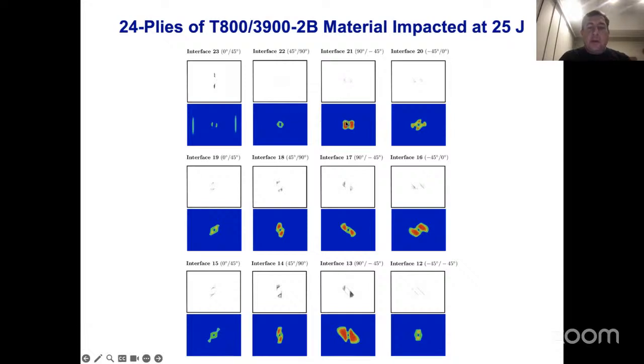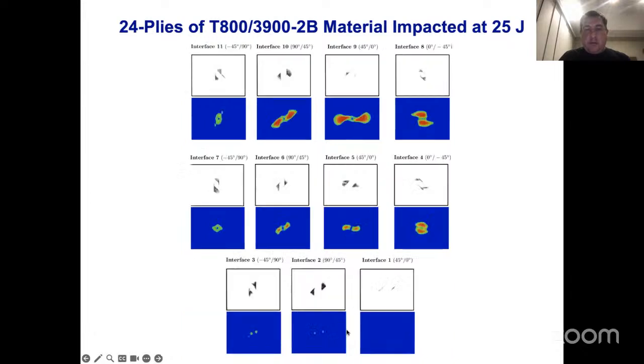And so here we're comparing the delamination patterns at 23 interfaces and comparing them to the CT scans. What you see is that the extent and the relative magnitudes in many instances compare quite well. So we're very happy with these results. You go to interface 11, 10, etc., all the way to the end. And again, we're not seeing as much delamination on the very last interfaces at the rear as we should. But you can see everywhere else, the agreement between what you see on a CT scan and what we predict in the calculation is quite good.